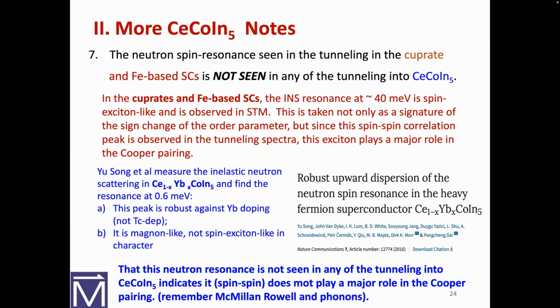I also want to remind you that the cuprates and the iron-based superconductors don't have f levels. And I've been believing that since I had to give an invited talk at an AAAS meeting two or three decades ago. And that's when I came up and said, there's not one mechanism. And people hate that because they think Occam's razor. But we already know N is greater than 2. So that's an argument that there might be other mechanisms. And that's what makes this field so difficult. As Dirk van der Marel would say, you add a little paprika, a little salt, spin, there's a few phonons in there. It gets very difficult.